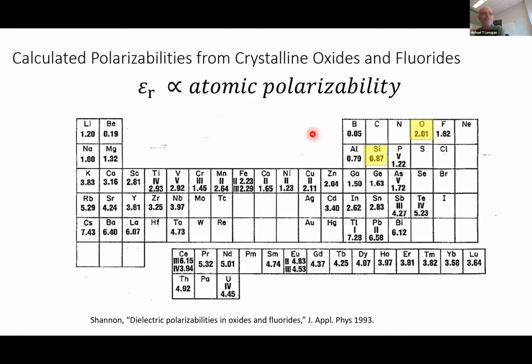And so in this case, for quartz, we can then take the polarizability of SiO2. You take 2 of these oxygens, so that's going to be 4. And then you add silicon, so it's going to be somewhere around 4.8 something. So that's the polarizability of silicon oxide.